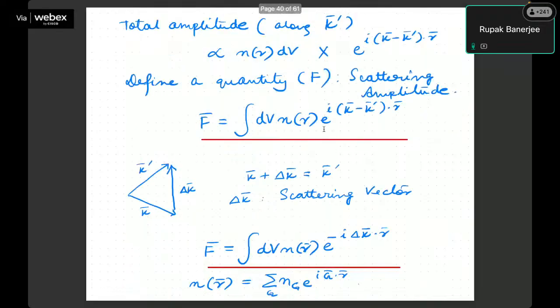So finally, if you look at the total amplitude along k prime, it should be proportional to not only the electron density distribution along this dV, but also to the phase factor. And this is where we define a quantity known as the scattering amplitude, F, which is nothing but the integral. Now you found it for an elemental volume, you integrated over the whole thing. So you integrate over dV n(r) e to the power i (k minus k prime) dot r. So this is essential. The scattering amplitude is this.